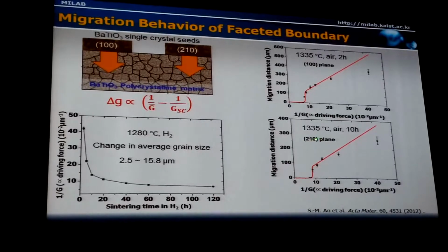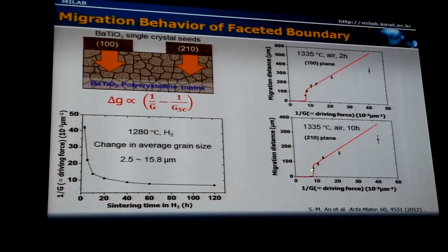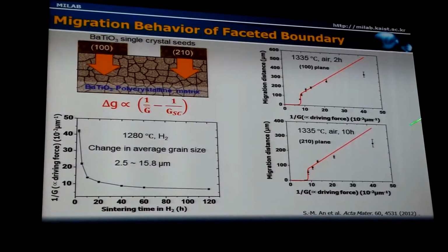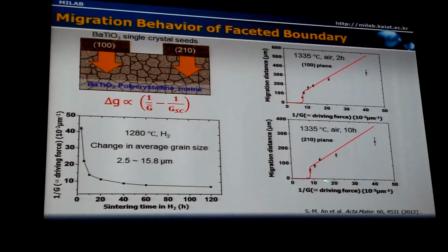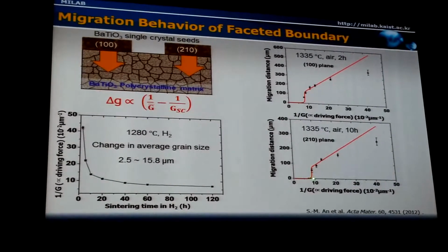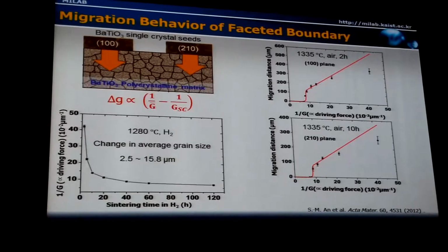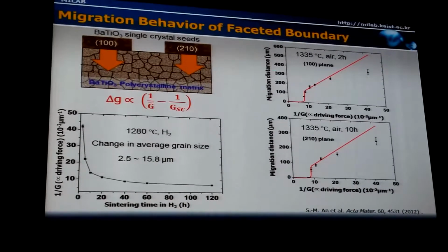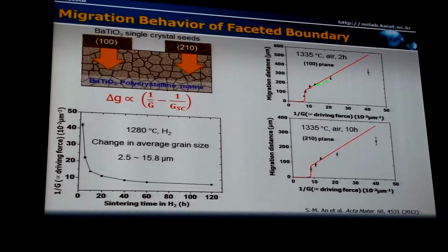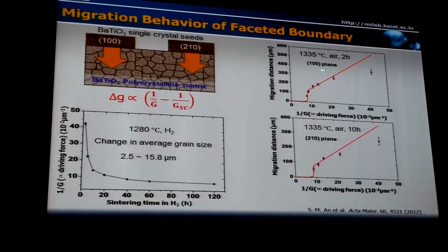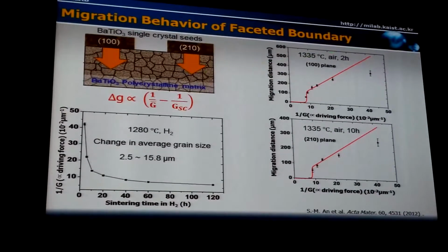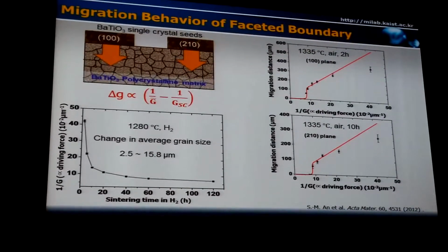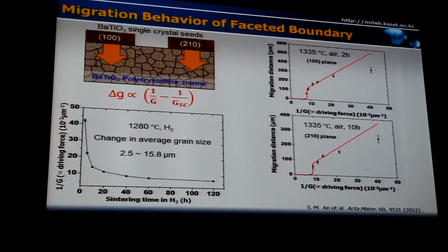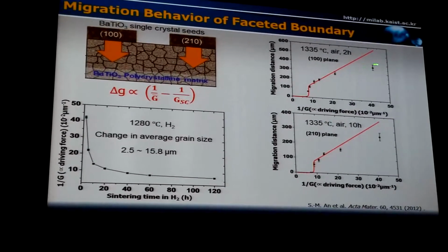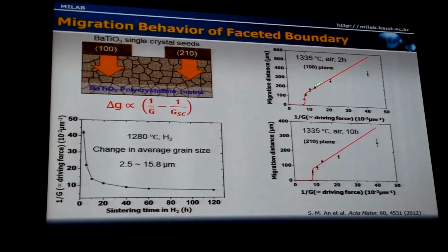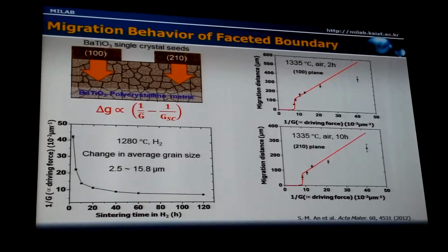Similarly, in the case of 2-1-0 plane, the migration distance is more or less linearly proportional to the driving force, and when the driving force is smaller than the critical value, then there was no migration. And there was a deviation from the linearity because of the segregation of impurities at the boundary. When the impurities accumulate, the diffusion kinetics, of course, is decreased. That's the reason why there's a deviation in the linearity of the measured values.